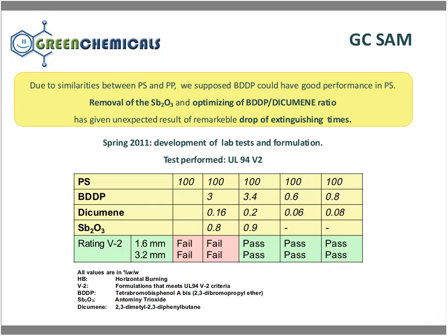So we started our study with a comparison between polystyrene and polypropylene, and we carried out some lab tests, some V2 tests. We took the existing technology that was in the polypropylene and we put it in the polystyrene. We looked at many different molecules, but at the end we found that BDDP was the most suitable solution according to different aspects, the commercial and the technical ones.